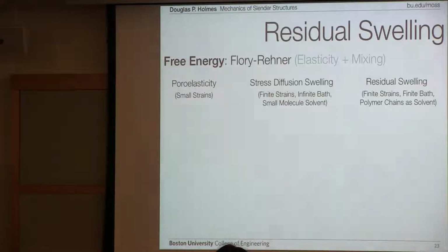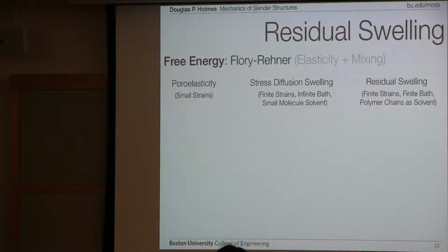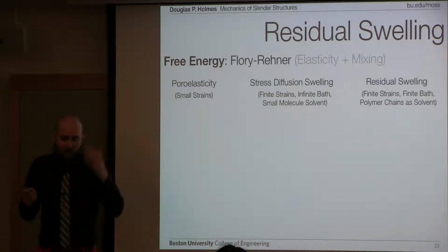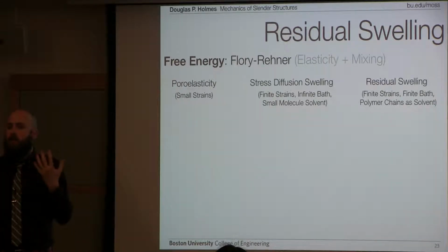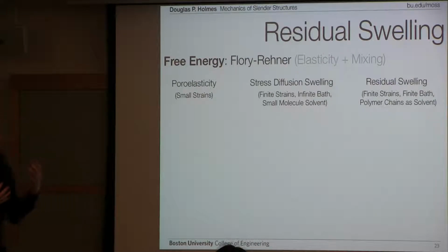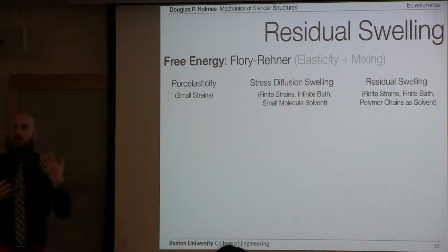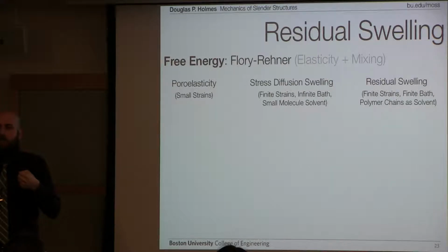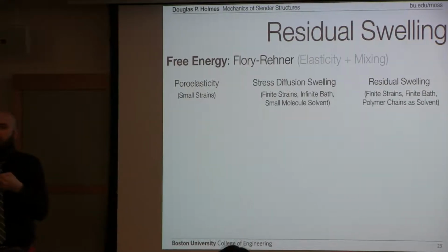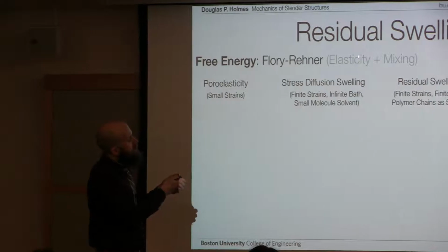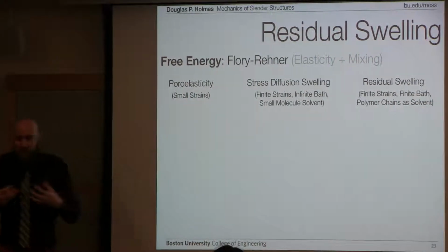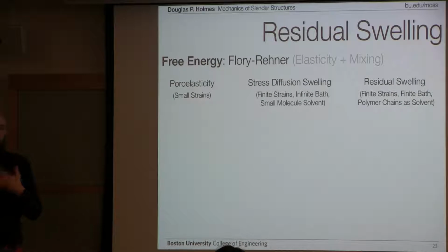So what's residual swelling? It helps to know a little bit about what swelling is. Swelling, you can think of as combining two different energetic things. One is contributions to the free energy due to elasticity, so the strain energy being stored in a material. And the second is a mixing component, which is to say, how much energy does it cost for these free chains to mix and intermingle with that elastic network? In the limit of really small strains, you can develop a poroelastic model for swelling.